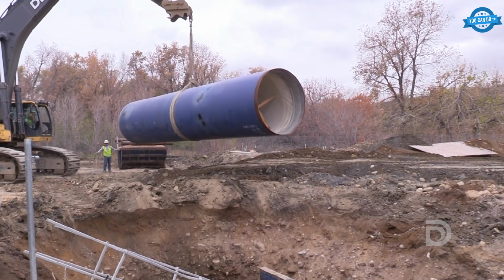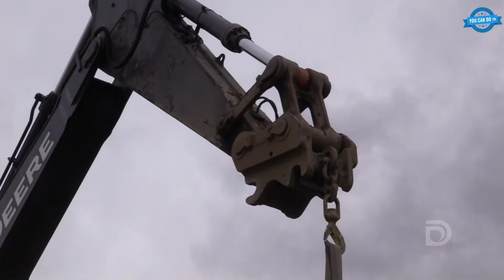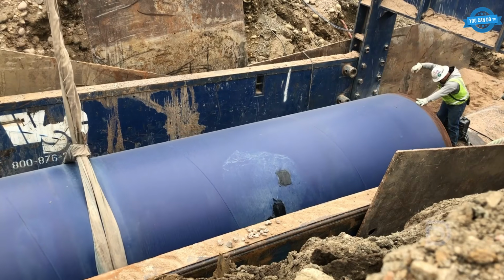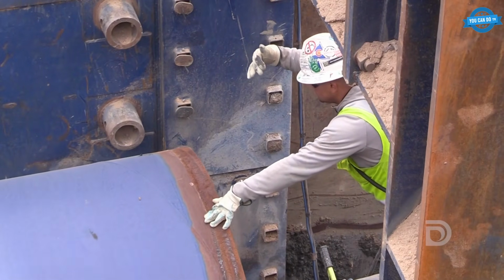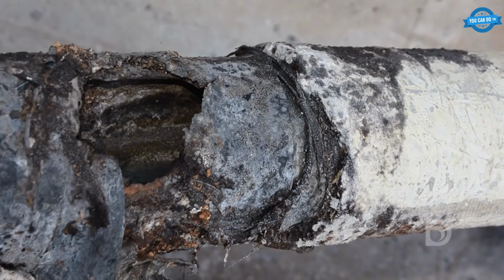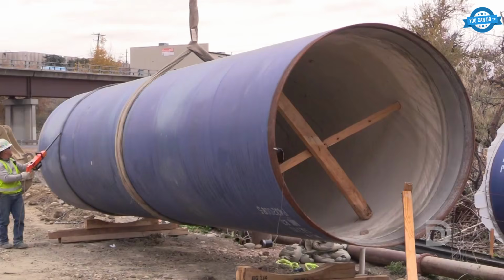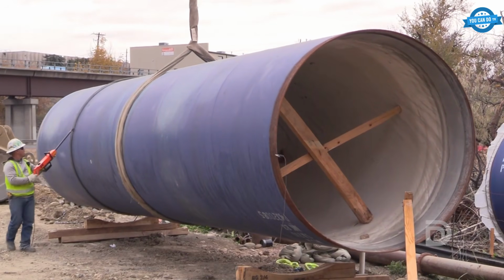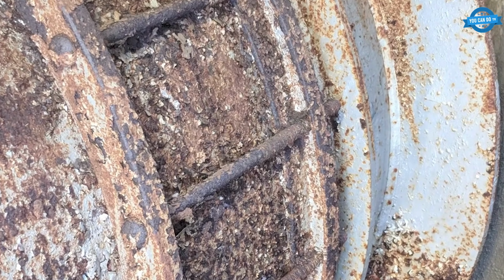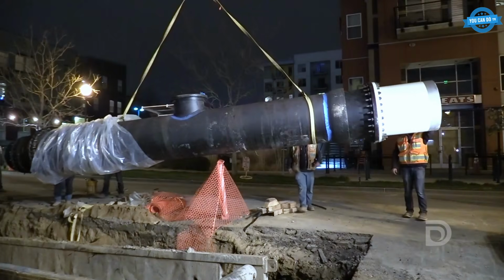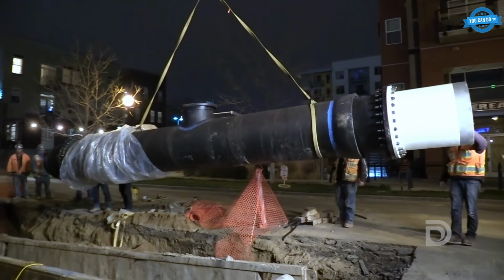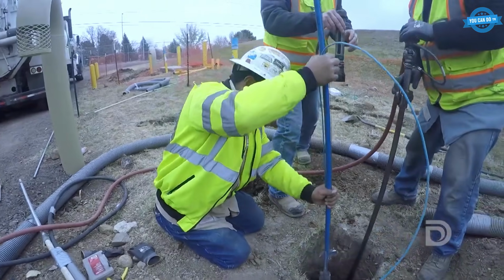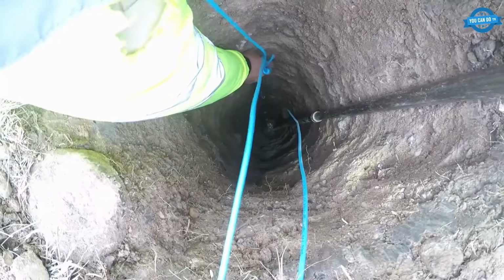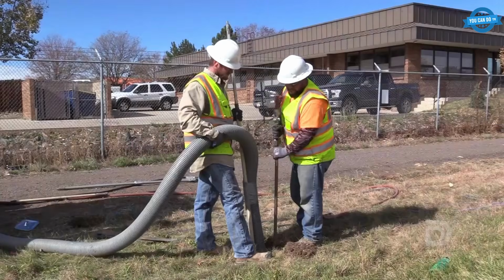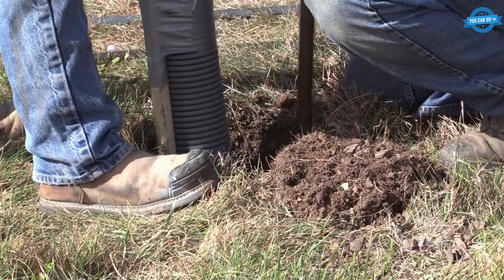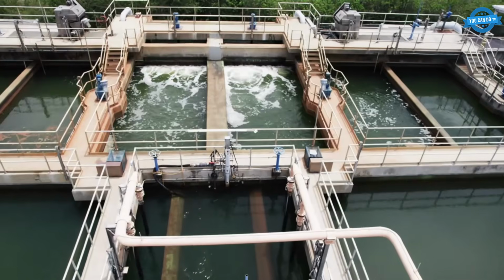Steel pipe rusts. Buried in soil with moisture and oxygen, it rusts faster. Cathodic protection moves the corrosion off the pipe onto something else, intentionally. Magnesium anodes are buried near transmission pipelines 2 feet in diameter and larger. Each 48-pound block is wired to the pipe. The magnesium corrodes preferentially while the steel stays intact. A single installation extends pipeline life by up to 25 years, with hundreds of test stations added each year.